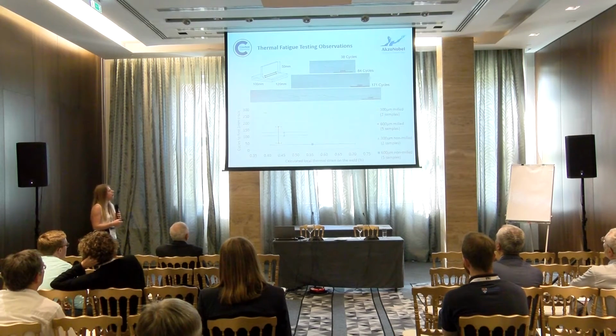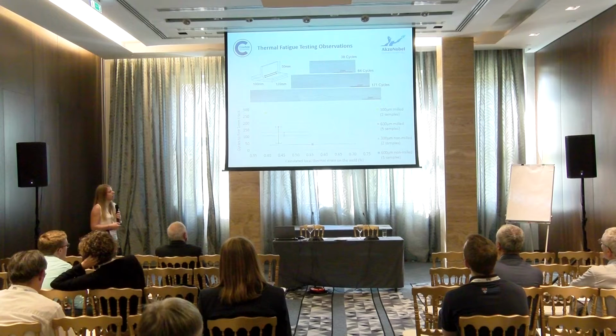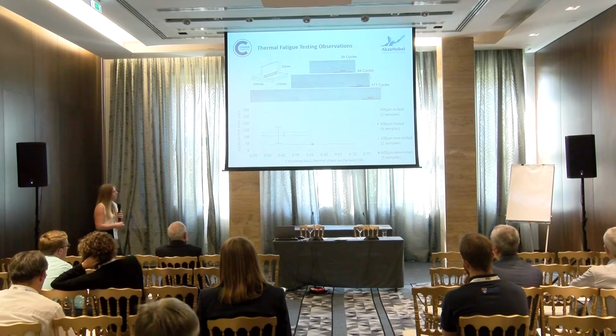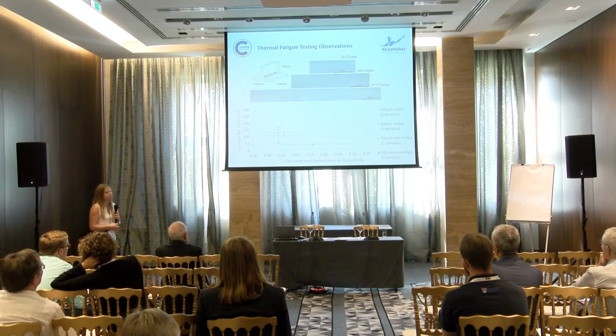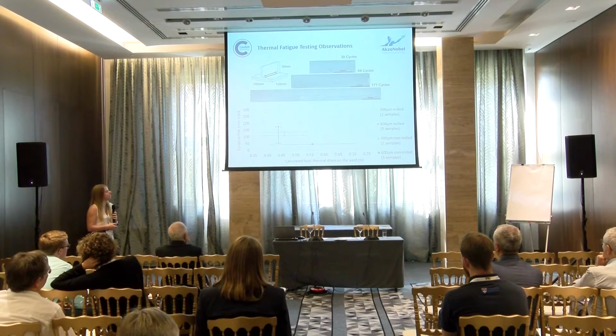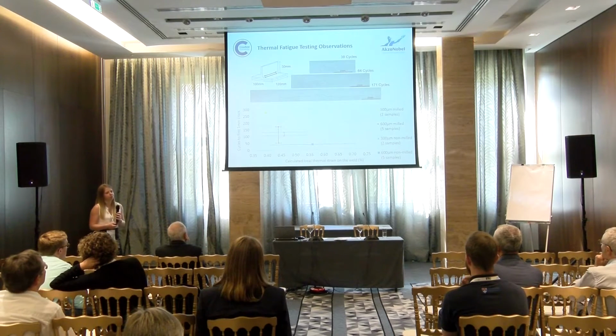So if we compare the cycles to first 1 millimeter crack identified for our 4 conditions, the conditions being 600 or 300 microns applied to milled or non-milled welds, and we introduce the thermal strains investigated using the finite element, we start to see a trend on how the local strain will affect the cycles to first millimeter crack.